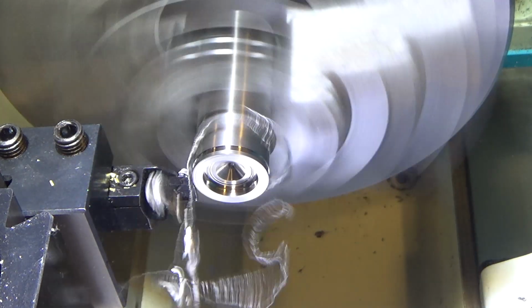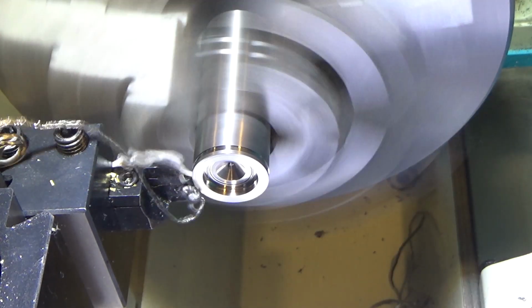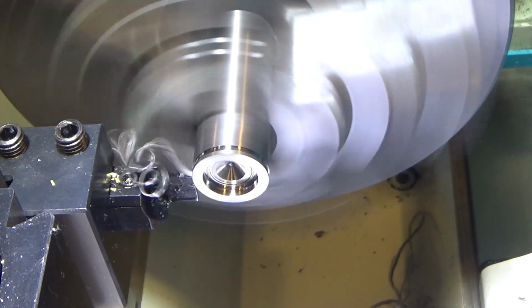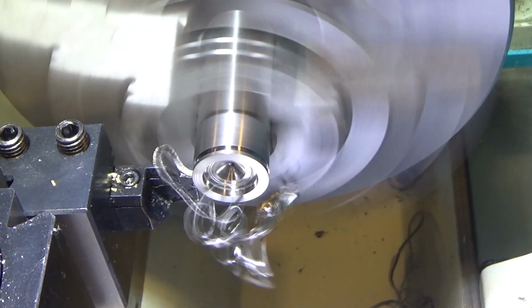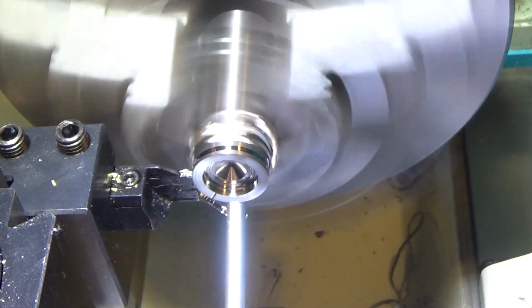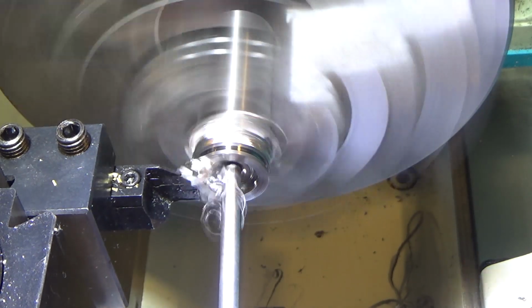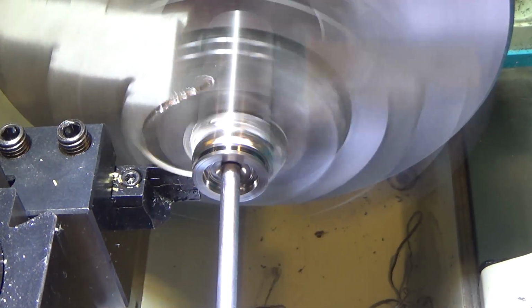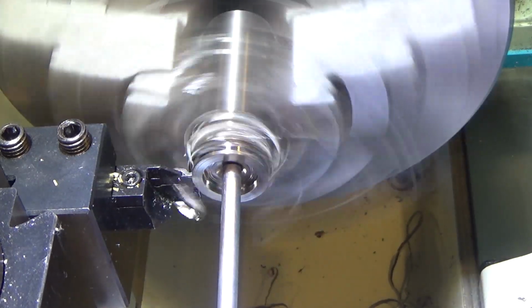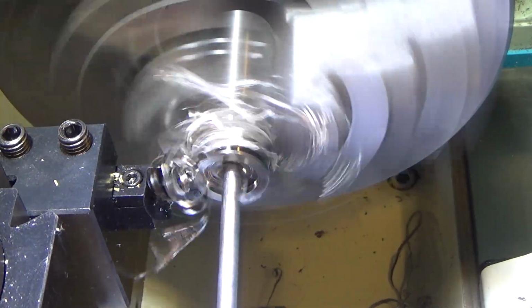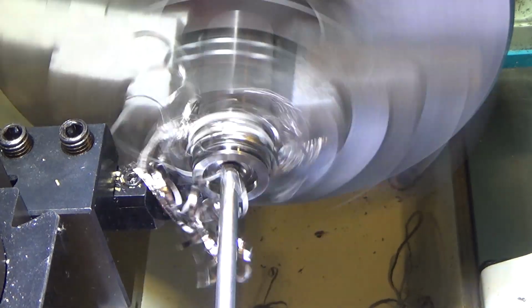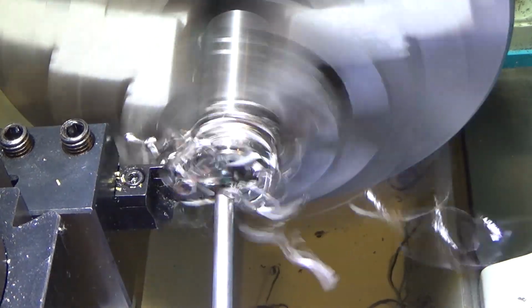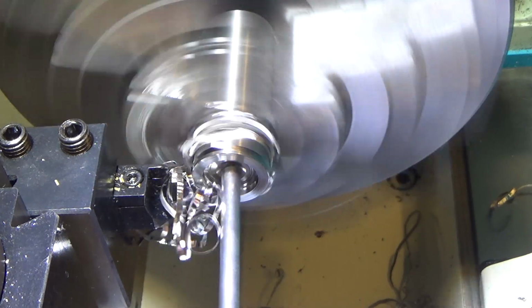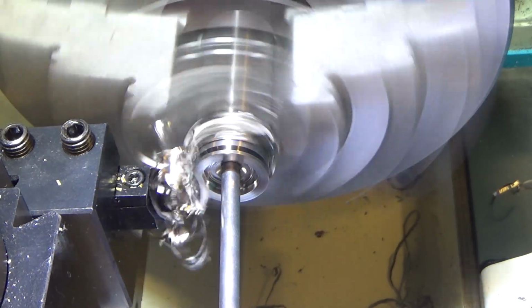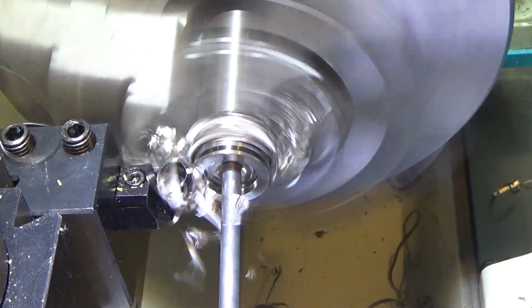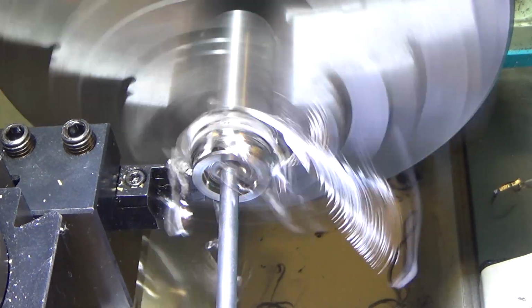You might be wondering why during a parting operation I'm not using lubricant, and it's because the titanium gets so hot that it starts to burn the lubricant. So what I really need is coolant, and I really haven't gotten up the guts to use flood coolant in my lathe yet because I'm worried about rust. So I do it dry, and it works out okay. But I got to be careful because I did see a couple sparks a couple times, and I think it'd be possible to ignite the swarf if you're not careful.